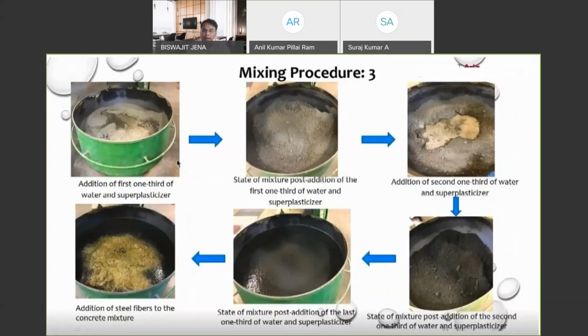Then add the first 1/3 of water and superplasticizer, mix it, and then add the second 1/3 of the water and superplasticizer. So you have added 2/3 of the water and 2/3 of the superplasticizer, and see how the mix looks. Once you add them, the right bottom mix, and then between that, the next, when you see the difference, that is purely by high shear mixing. So you have just mixed it for 5 to 7 minutes, extremely high shear, to break all the particles and to release the water from all the agglomerates.